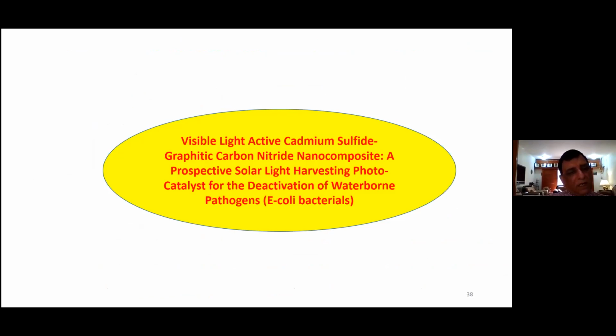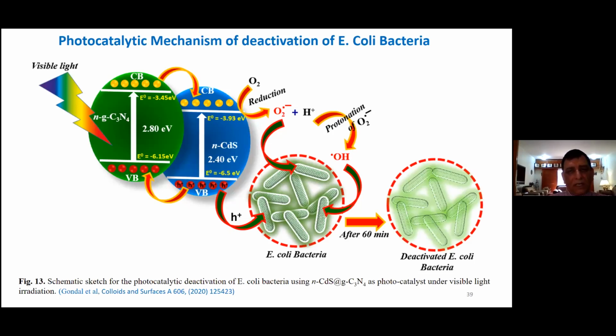Now I go to the third experiment, where we are working on killing E. coli bacteria, which is very dangerous for urinary tract infection. We have also used a catalyst here, cadmium sulfide, with graphitic carbon nitride loaded on it. And we can see clearly how our excitation scheme works. We have CdS on the right side, and we have graphitic carbon nitride. CdS has a 2.4 electron volt band gap in the visible region, while this one is close to the UV region. When we generate these radicals, O2 dot minus or OH radical, it attacks the bacterial membrane. Bacteria are organic matter, so the bacteria are completely deactivated, which I can show you later in the results.